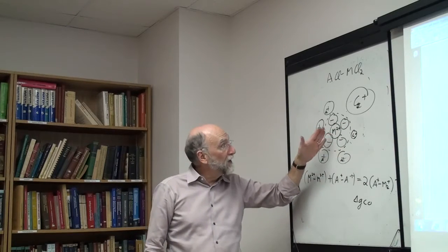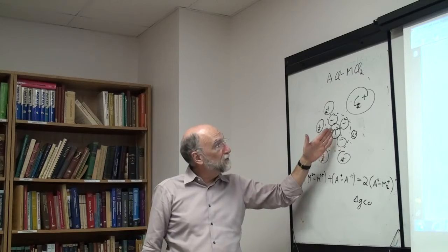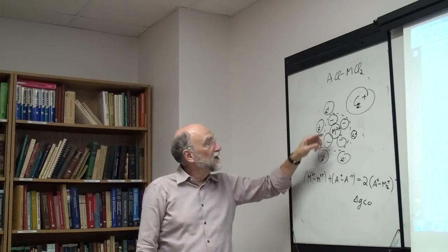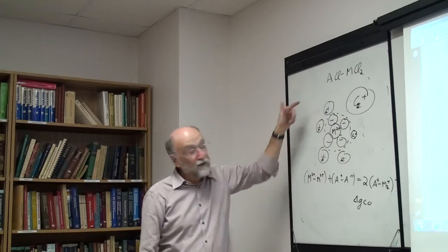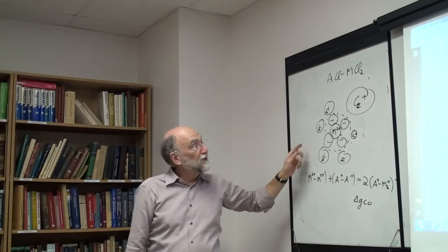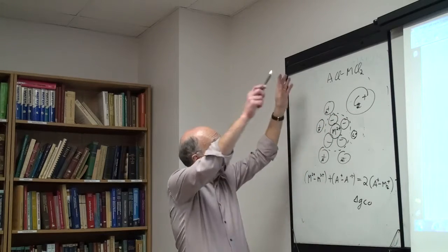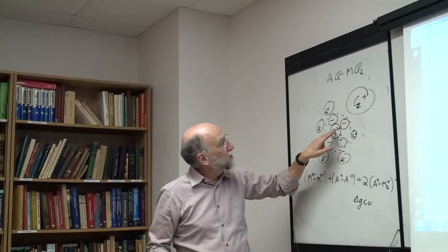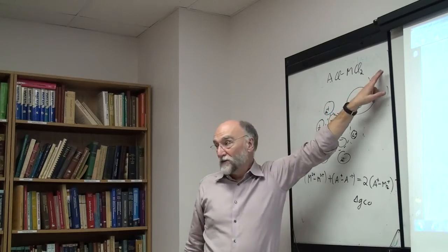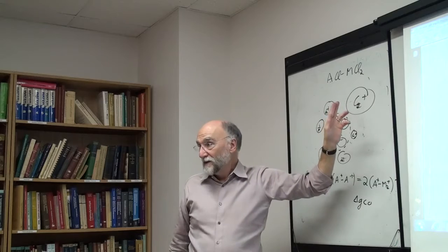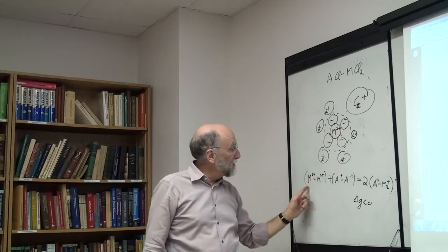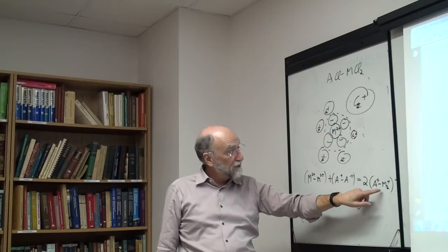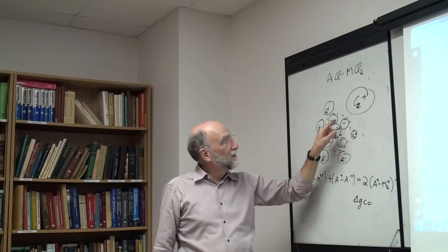So you're going to try to minimize the magnesium 2+, magnesium 2+ interactions, and you do this by putting cesium in the second nearest neighbor shell. If the second nearest neighbor shell is a big ion like cesium, then the next M2+ is way over here, so the MM interactions are being minimized by replacing them with a large ion. These are very weak.